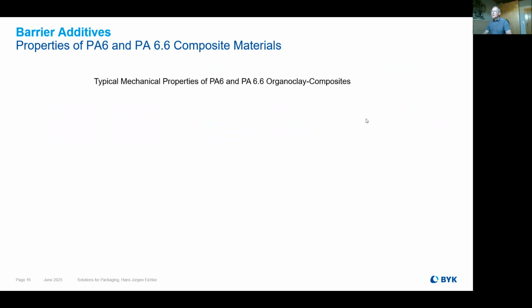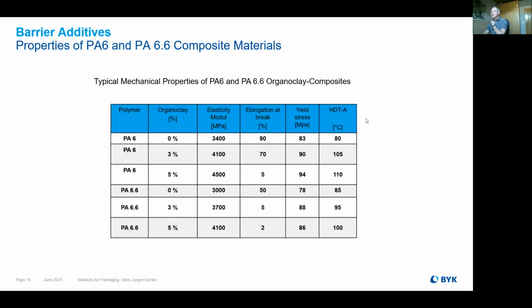So if we start now with polyamide 6 or polyamide 6,6, and doing a compounding job with our clays, you get now an idea what it means if we introduce a material. You see it behaves more or less like a filler. You see here there's a virgin material with an E-modulus like that, and if you start with 3 and 5% of the clay, you increase the E-modulus, but you will dramatically reduce the elongation at break. And of course, you will increase the HDT, which might be nice. And so in principle, the clay is behaving like a real mineral.